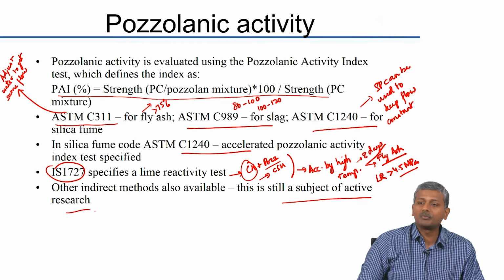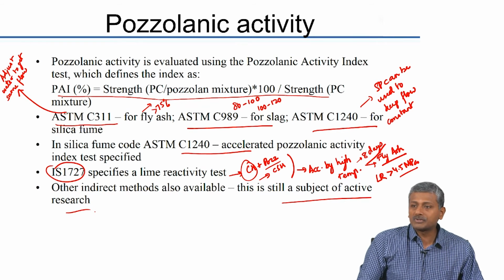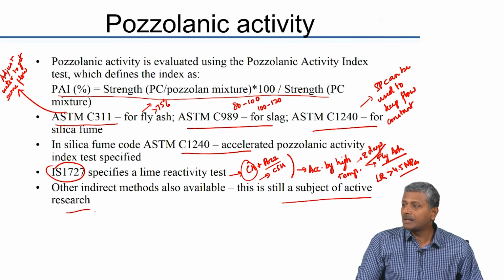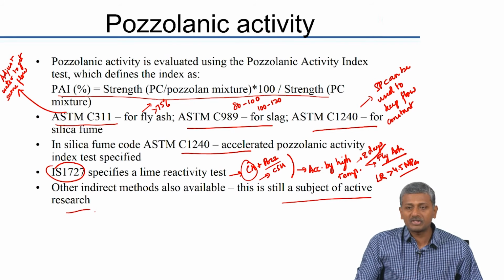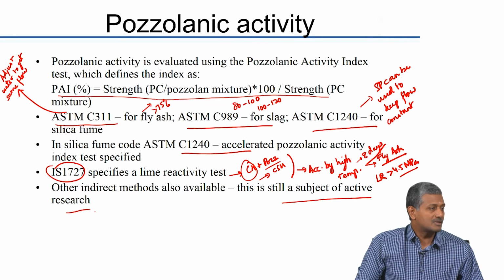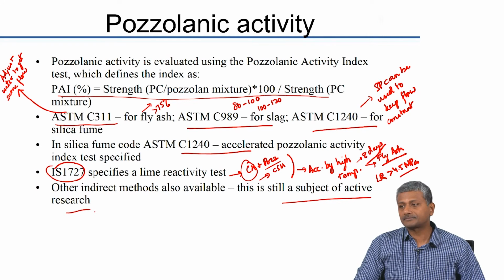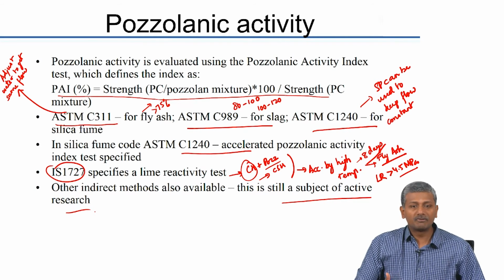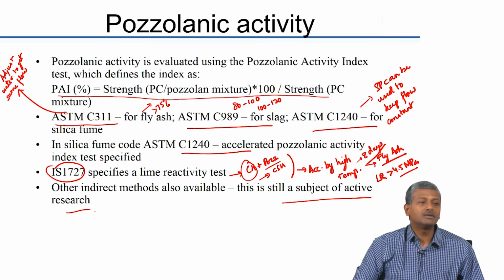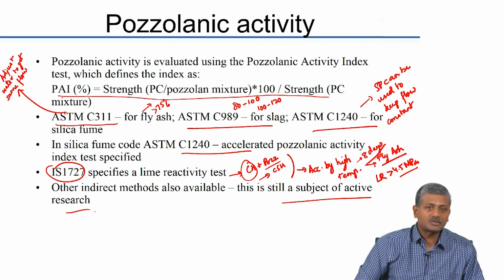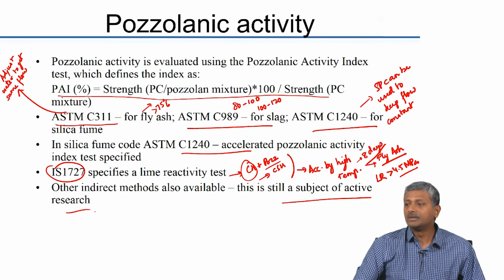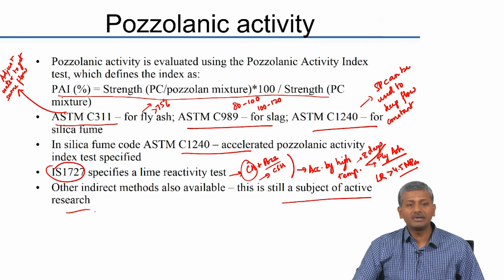For example, with silica fume mixes, the reaction of the pozzolan is so fast, but then the lime availability from the cement is not matching that reactivity. That is why the silica fume system still takes some time to reach the level of a cement system. So, if you can accelerate the generation of lime from cement, then you can accelerate the pozzolanic reaction. That is why high temperatures generally tend to improve the rate at which your pozzolanic system will react.